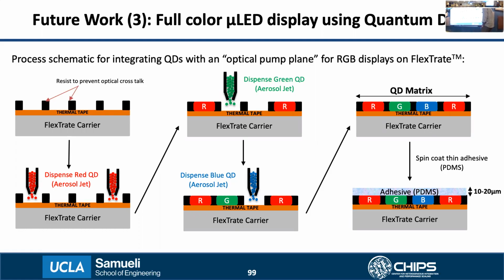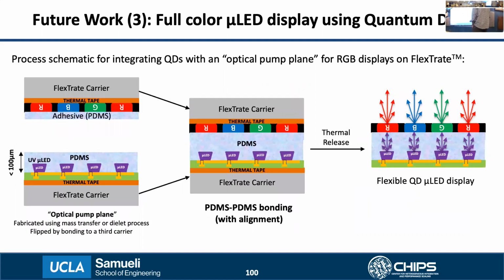And then once this quantum dot matrix is defined, we can spin coat an adhesive on it, such as PDMS. And then we can take this color conversion layer and 3D stack it with alignment on top of a flex substrate fabricated micro LED display, which is what the majority of this talk was about. But here the micro LEDs would be UV LEDs because they would be more efficient and they can excite the quantum dots to generate the 3 colors. Once these are aligned and 3D stacked and we release the carriers, we get this optical pump plane of micro LEDs, which will generate UV light that will excite and create the 3 colors for a full color display.